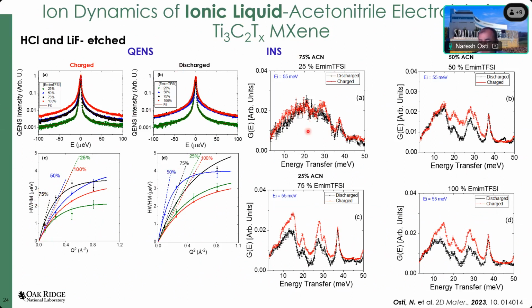And we also collected the inelastic neutron scattering spectra for the same system. I'm not going to go into detail, but what you can see here is that the scattering intensity is higher for the charged system. It means that most of the ions get attached to the surface of the electrode once you charge the system. That's the information we got from inelastic neutron scattering.